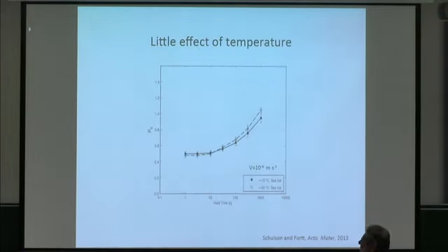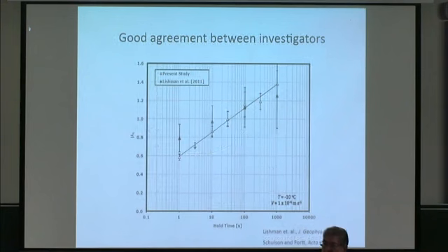Not only does salinity have a little effect, temperature doesn't have a very large effect either, curiously, at least over the range of temperature from about minus 10 to minus 30 degrees centigrade. A little effect, but we're not going to worry too much about that. What else?